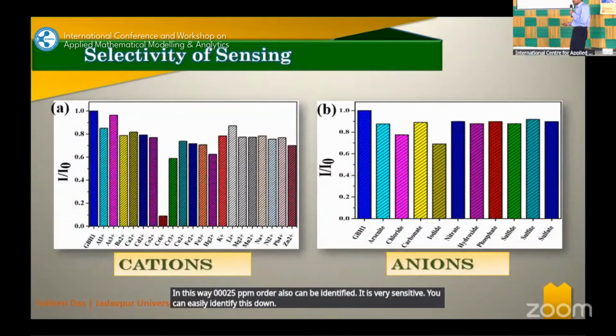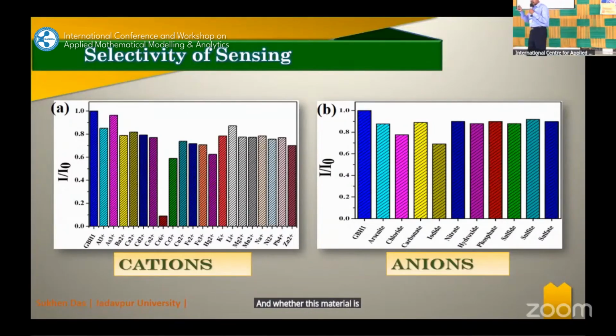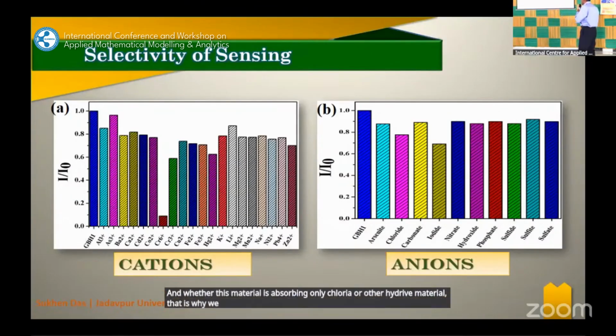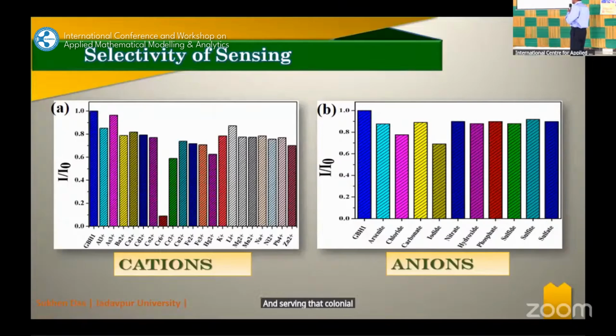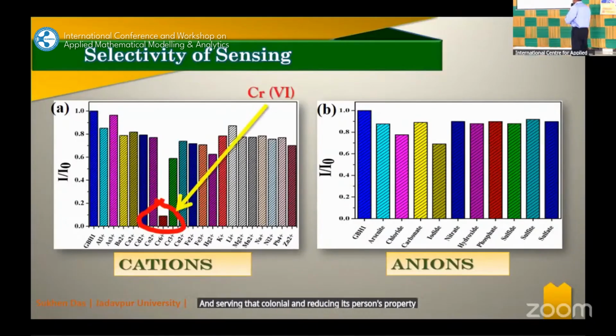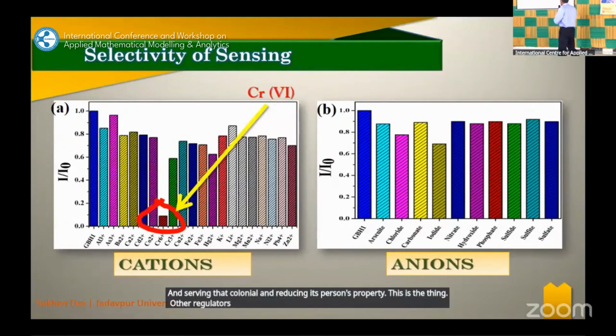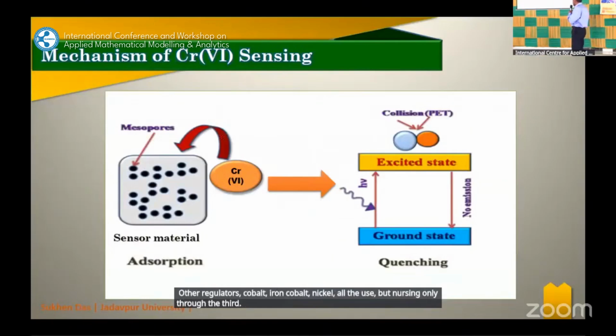And whether this material is absorbing only chromium or other heavy metals, that is why we tested this with other heavy metals, but we have seen that this material is only absorbing the chromium and reducing its fluorescence property. Other heavy metals, zinc and iron, cobalt, nickel, all we have used, but we have seen only chromium is absorbed. So what is happening there?